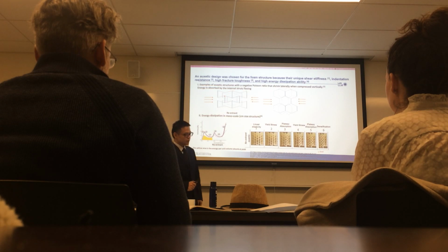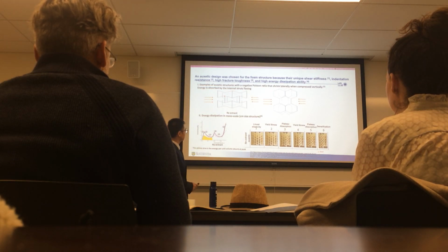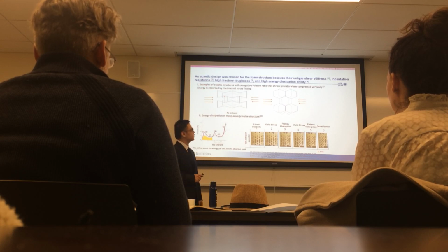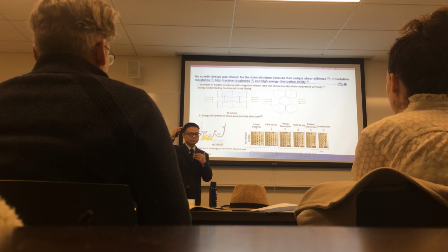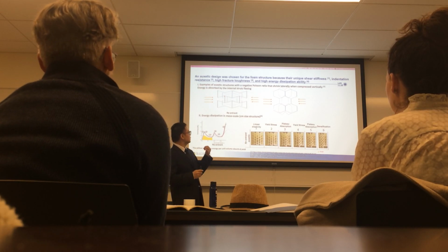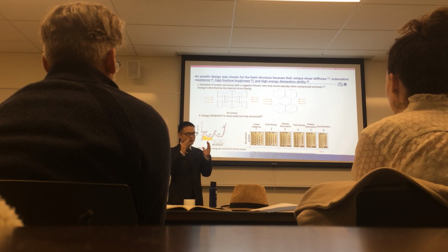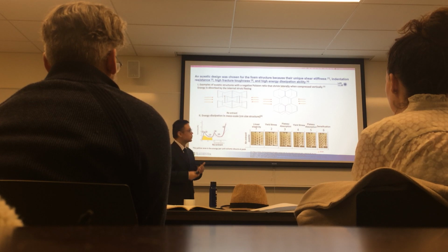Okay. After we have the printer, we need to decide what kind of unit cell we want to print out. We use this structure as our unit cell because it has a very novel behavior. It causes a negative Poisson ratio behavior. A conventional structure just has a positive Poisson ratio behavior. When you compress a foam structure in one direction, it will expand in another direction with the normal structures. But for our structures, when you compress in one direction, in another direction you have a shrinkage. Because of this novel behavior, we can figure out this structure has a high resistance and high energy dissipation abilities in the mesoscales.